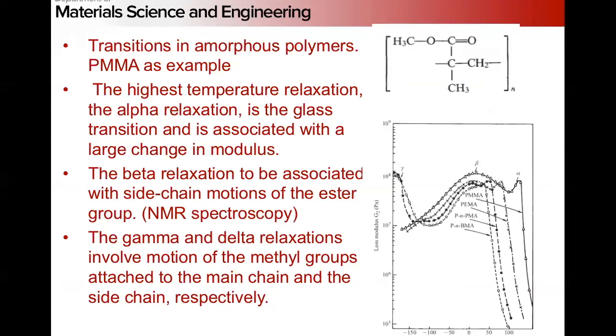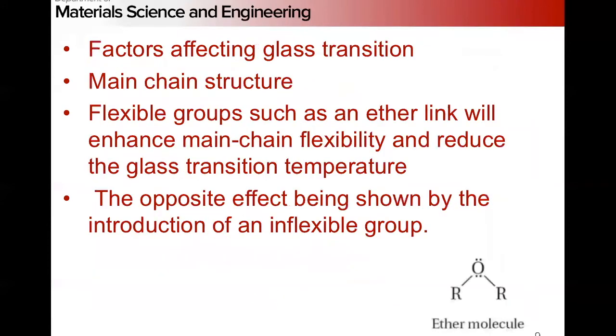So when you're going through the reading, pay careful attention to what the graphs are actually showing. The loss modulus basically gives us the amount of energy that's going to be dissipated by the viscous contribution of the behavior. So near the glass transition, we have a higher degree of viscous flow. As we cool down, we get somewhat less. Increase, decrease, increase. This is why polymers confuse me. You get these strange behaviors. From a mechanical point of view, the glass transition is much more important than those secondary transitions. We're not really going to worry about those much anymore.